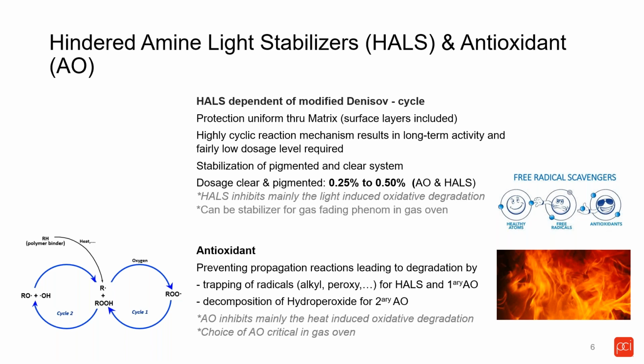Now, because we don't have the Beer-Lambert principle anymore, there is no correlation anymore between the thickness of the coatings, the dosage of the hindered amine light stabilizer, and the performance. Also because we are following this Denisov cycle, which pretty much regenerates the nitroxide radicals, which is your active component of a HALS. The dosage of HALS is very often significantly less than that of a UVA. As you can see here, we recommend between 0.25 to 0.5%.